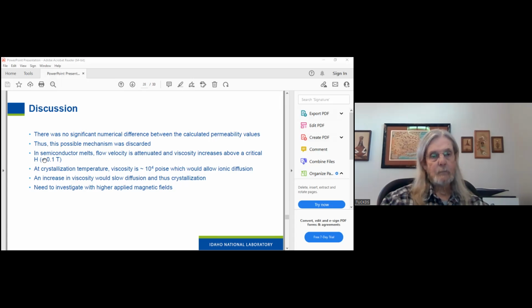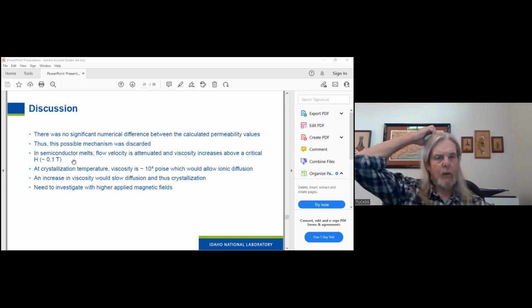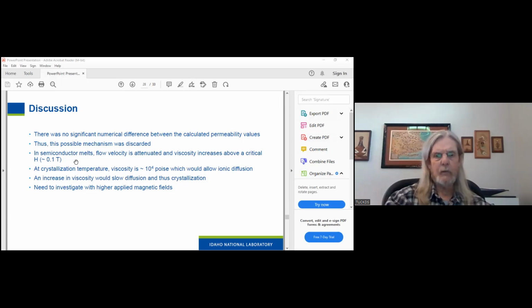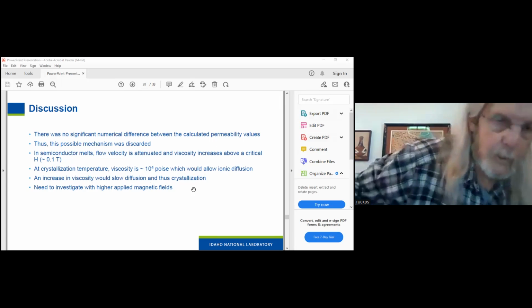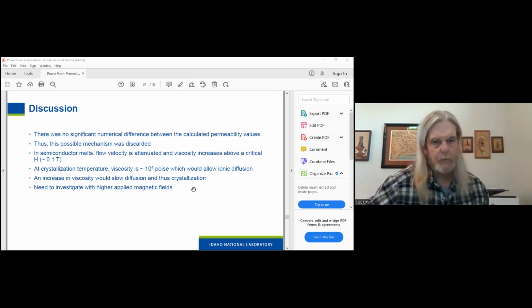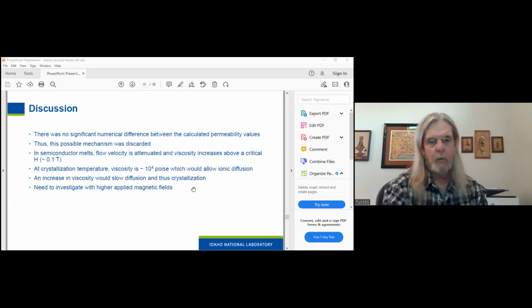Now, in semiconductor melts, for example, flow velocity is attenuated and viscosity increased above a critical magnetic field intensity, about 0.1 Tesla. At crystallization temperature, viscosity is approximately 10 to the 4th poise, which will allow ionic diffusion. An increase in viscosity would slow diffusion and thus crystallization. So what I need to do, and I'm waiting on funding for this right now, is to investigate the higher applied magnetic fields.